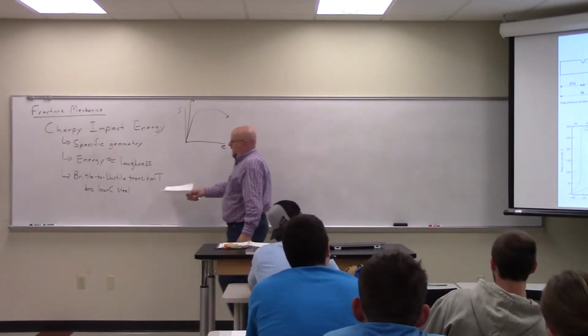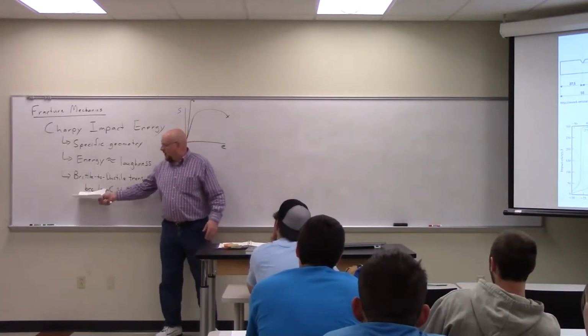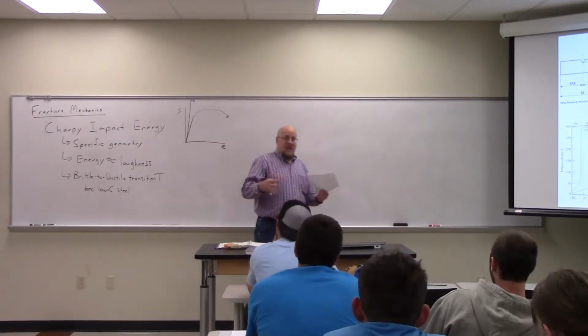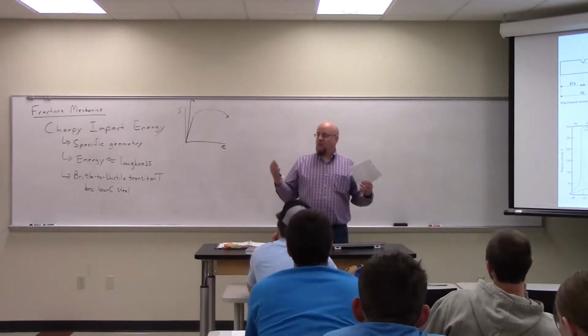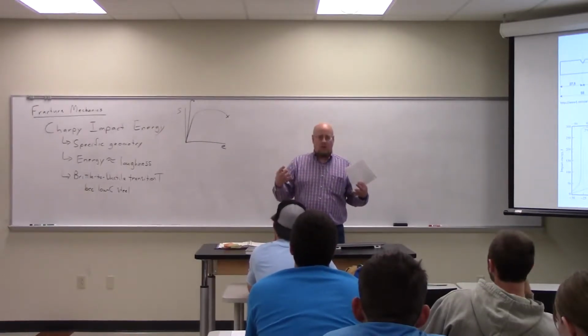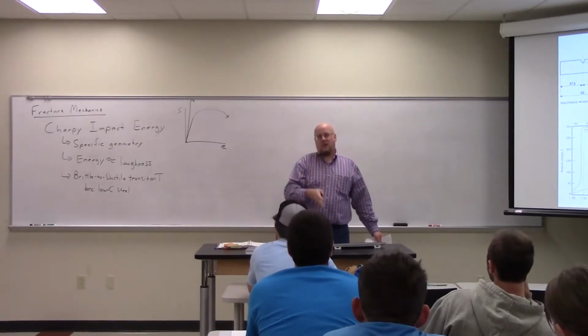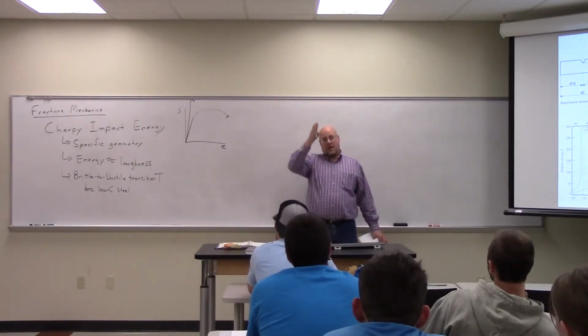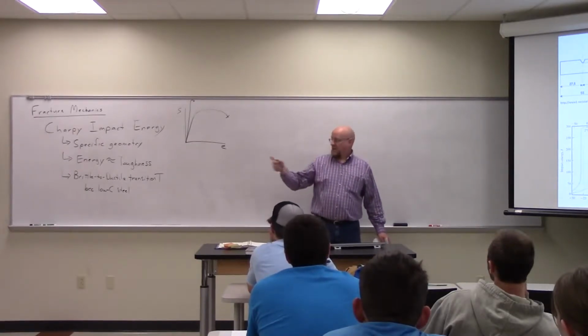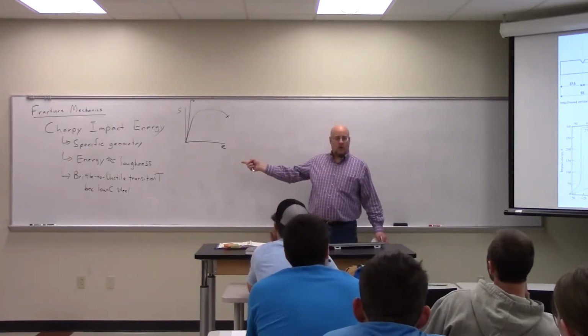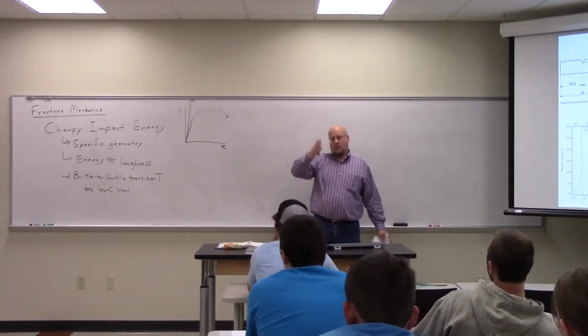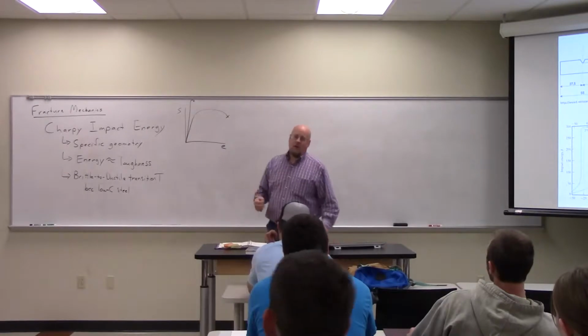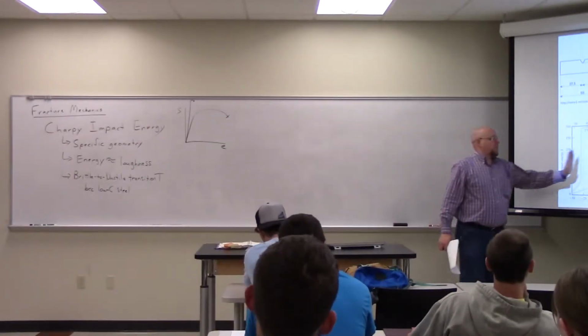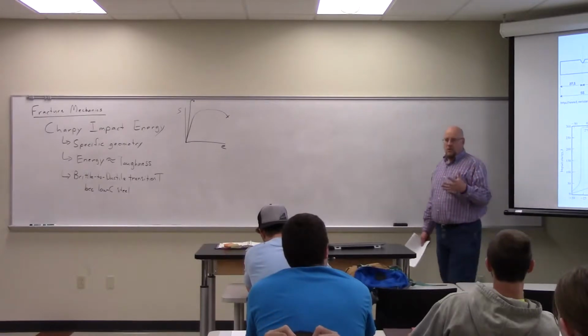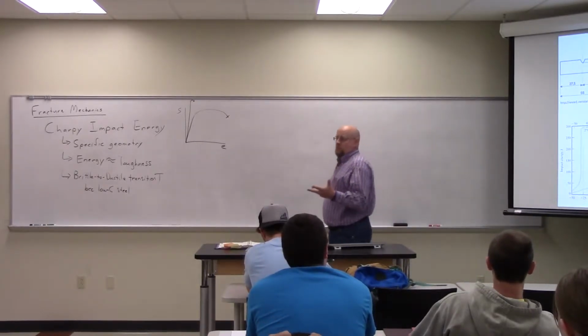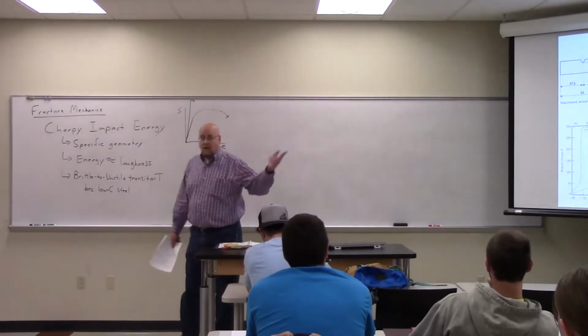Because again, we haven't really talked about heat treating much, but when you weld them, you heat them up and they actually change the properties of the material. To weld something, you have to melt some metal. And so you get really hot, and that section that used to be made of a different kind of material is now made of this low carbon BCC because it's been heated and allowed to cool and change structure. So now the weld regions are made out of this low carbon BCC steel, which experiences a brittle to ductile transition temperature in the neighborhood of where the cold water was. And so it was this brittle ship that literally just cracked in half.